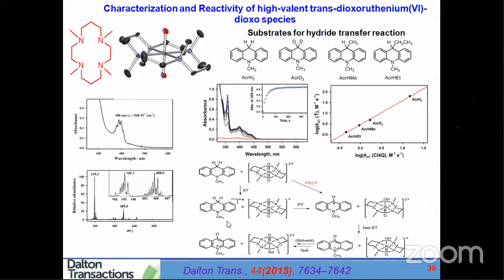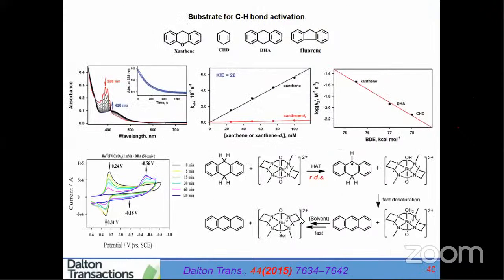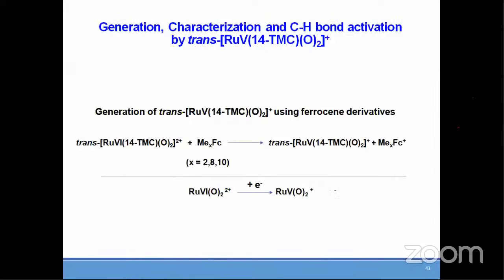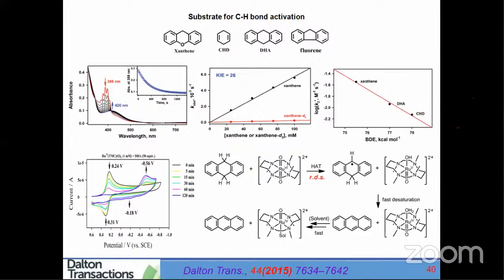In the acridine substrate, the hydride transfer mechanism is shown here. And for the hydrogen atom abstraction substrate, we chose this, and the mechanism was hydrogen atom abstraction as the rate determining step, shown here. Some steps we also showed by cyclic voltammetry. You can see a very clean and neat spectrum over here. This indicates that the reaction is taking place, so there is absolutely no problem. Of course, the only thing is final characterization. So this work will be published.